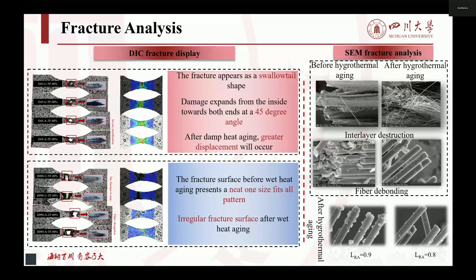This study utilized DIC technology and SEM for fracture characterization. The fracture images clearly reveal that the 45-degree laminated board after hygrothermal aging becomes more elongated, and the fracture surface presents a 45-degree angle, primarily due to the fiber orientation at 45 degrees. The fracture surface of the 90-degree laminated board after hygrothermal aging transforms from a neat straight cut to an angular shape, mainly because hygrothermal aging causes the fibers to no longer adhere together, leading to uneven stress distribution on the fibers.